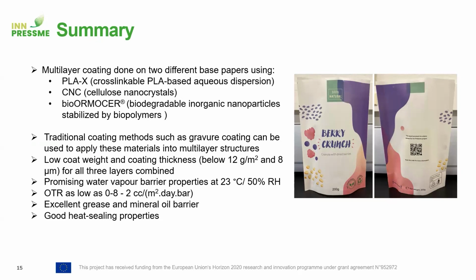Just to sum up, we made these multi-layer coatings using bio-based materials on two paper substrates, using PLA-X, CNC, and bioORMOCER materials that were produced at the INN-PRESSME pilot lines. We could use standard coating methods, and we also demonstrated that it is possible to coat these at industrial scale, and we reached very good barrier properties for both water vapor and oxygen.